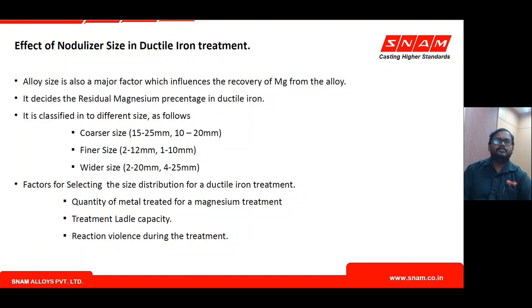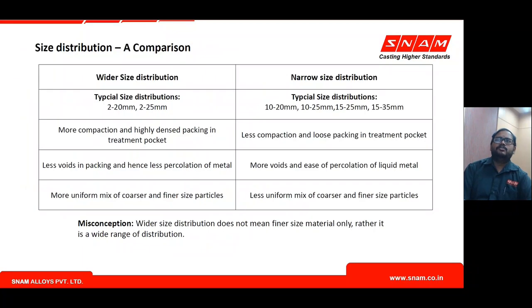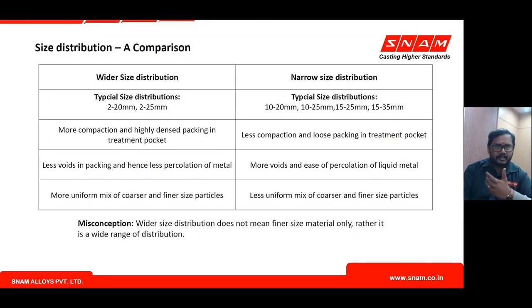Reaction violence during treatment also influences size distribution selection. When metal quantity, ladle capacity, and reaction violence are considered together, the appropriate size distribution can be selected to achieve maximum benefit and recovery from the available magnesium without increasing alloy magnesium content. Wider size distribution gives more compaction and higher packing density in the treatment pocket, while narrow size distribution gives loose, low-density packing.